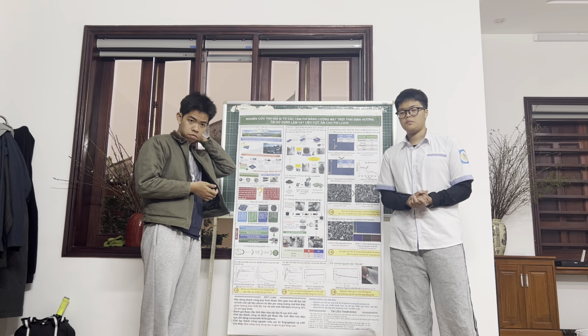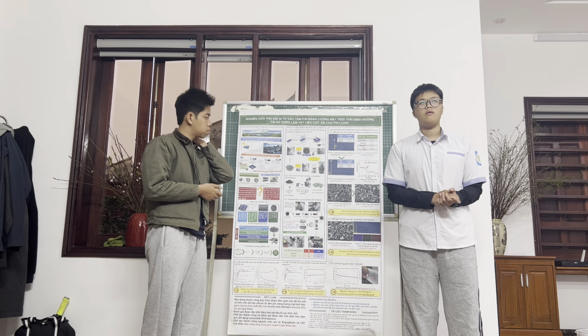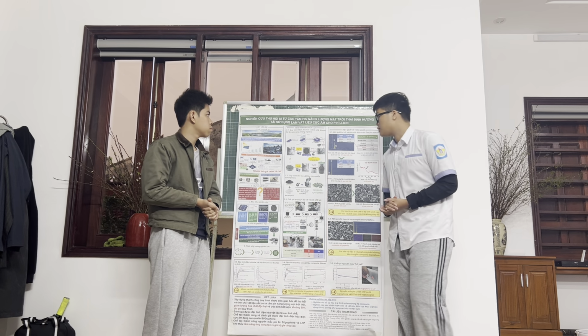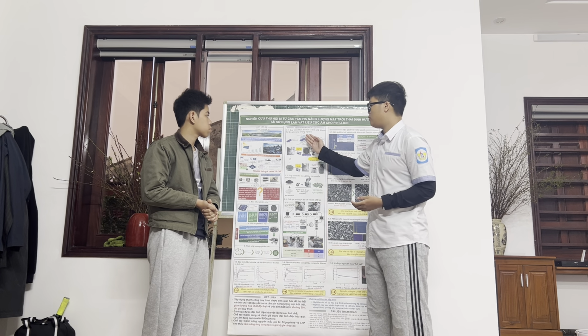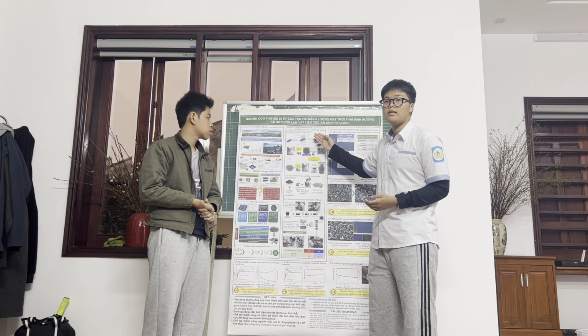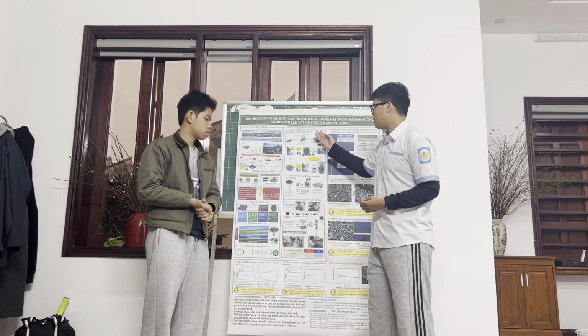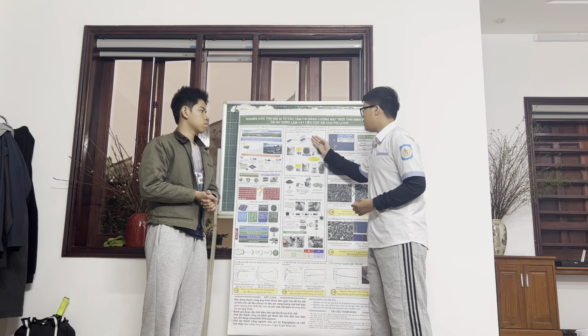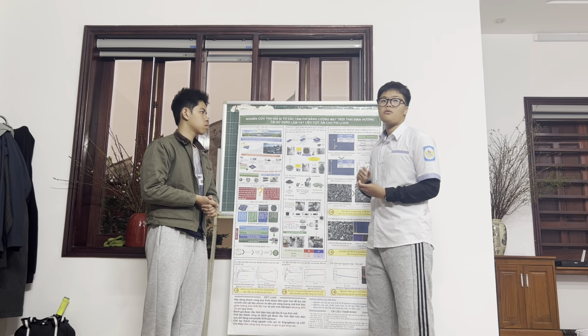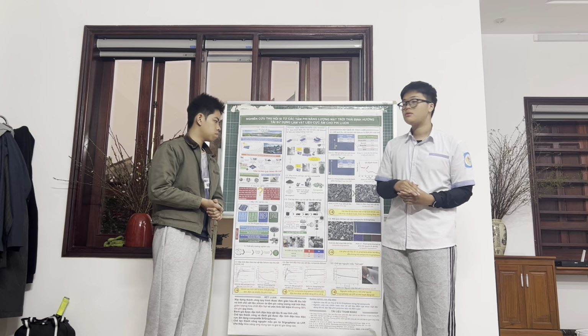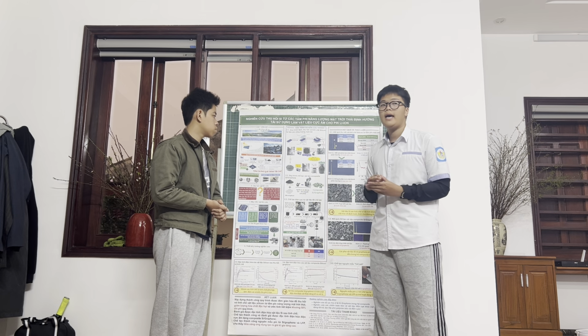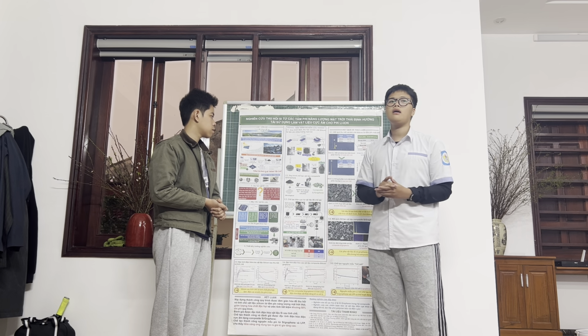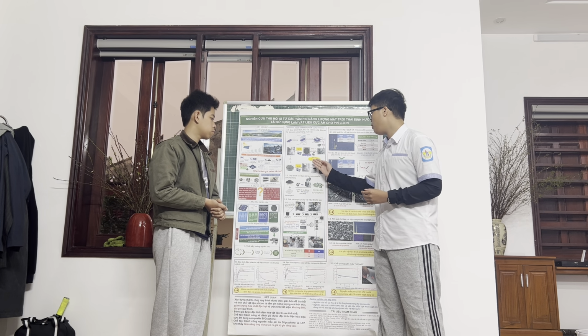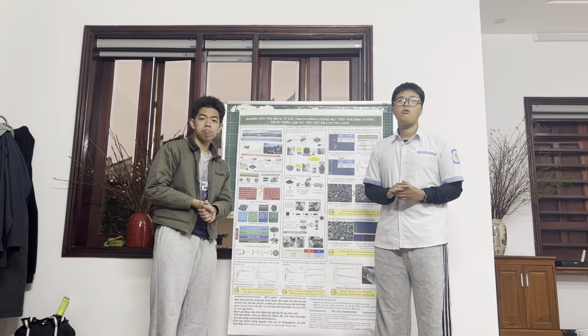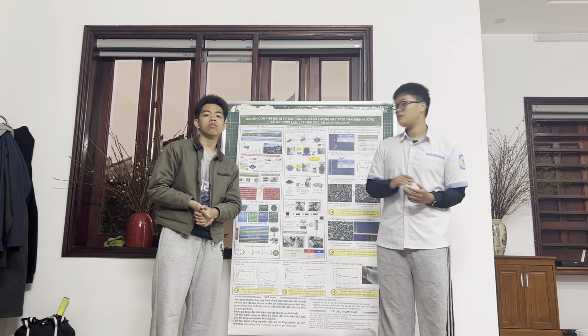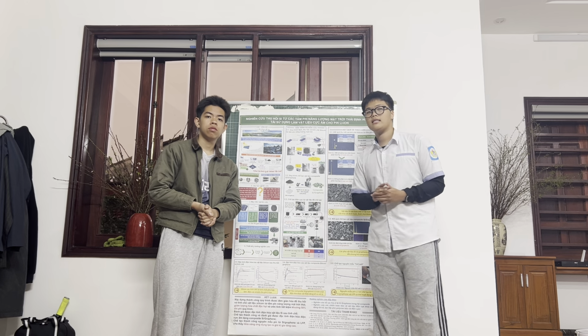Based on the objectives, the research process of the team is as follows. First, the silicon was recovered from the end-of-life solar panels with physical separation in section 2.1, followed by a refinement process using acid and alkaline solutions enhanced with sonication. The silicon samples before and after refinement were evaluated and compared using EDX, XRD, and SEM techniques.